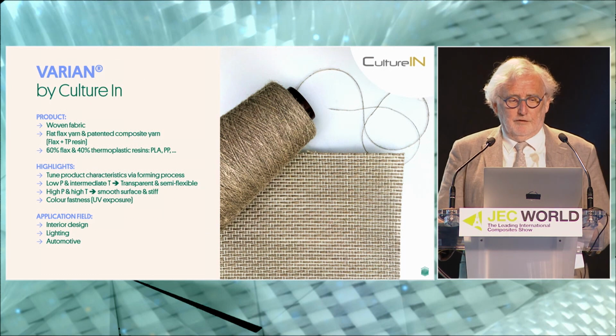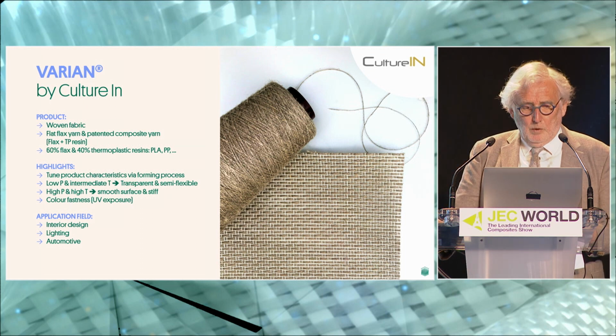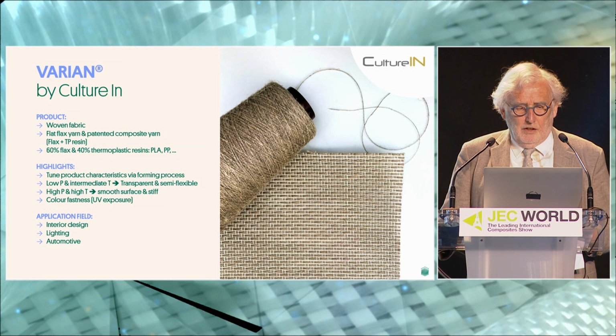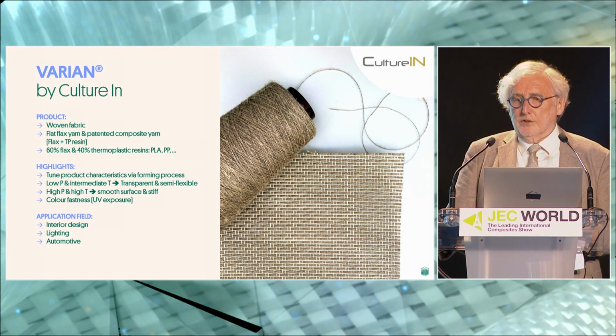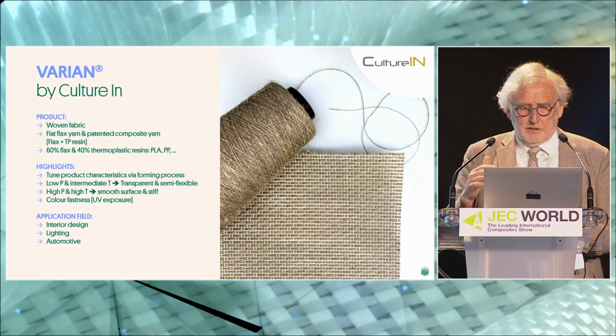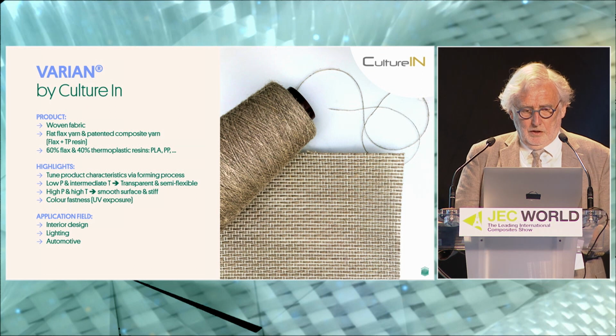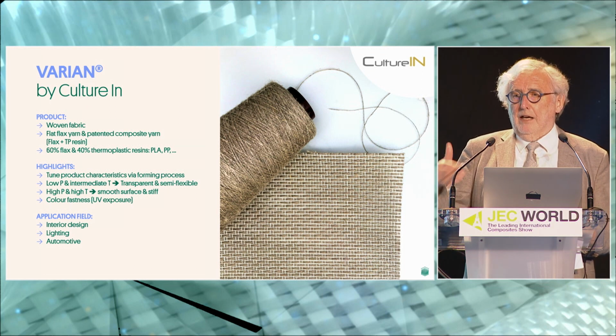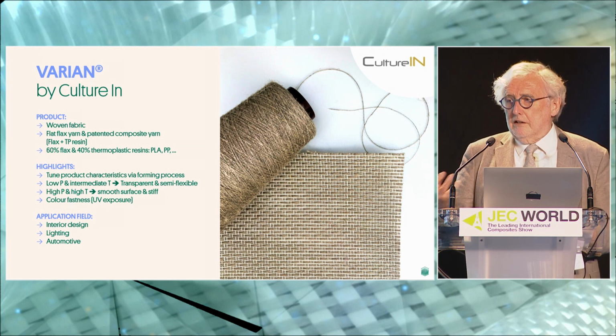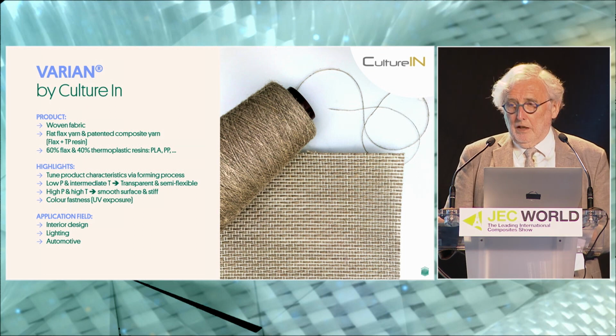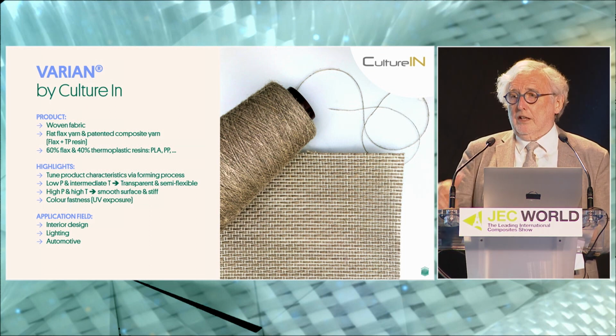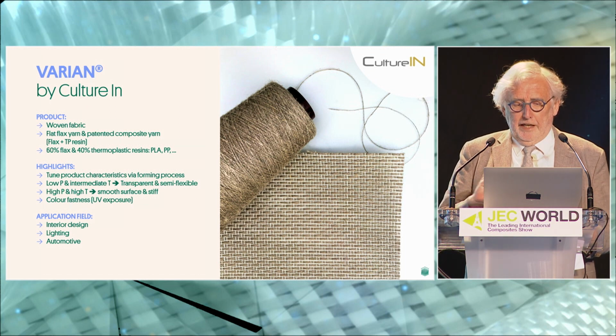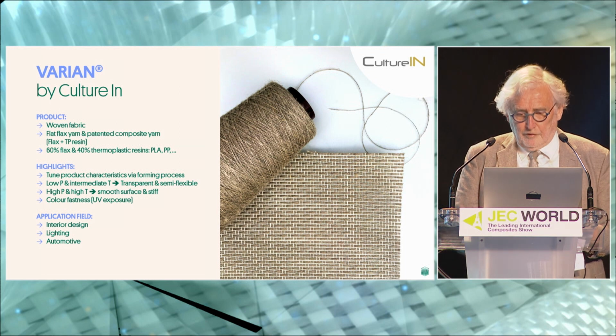And finally, there is this nice material, Varian, by the company Culture-In. It's a woven fabric, and it is a combination of a flax yarn together with a composite yarn, which consists of flax and thermoplastic. So it has overall 60% flax and 40% thermoplastic. Thermoplastic can be either PLA or PP or others. And the interesting thing is that by adapting the temperature and the pressure, you can create very different materials. If you use low temperature and low pressure, you have a kind of transparent, semi-flexible preform. If you increase both temperature and pressure, you get really a solid laminate with a smooth surface.